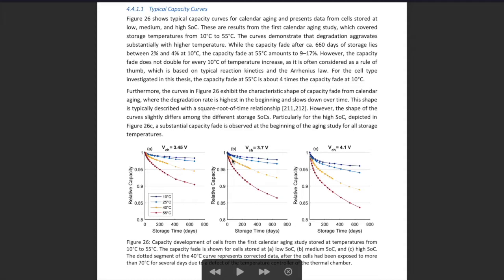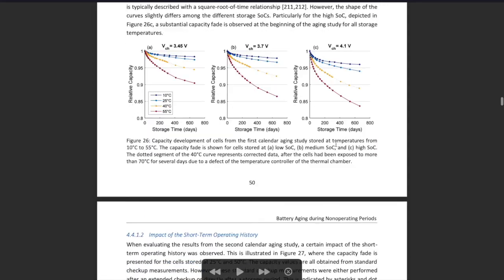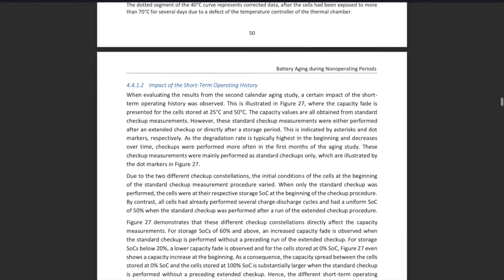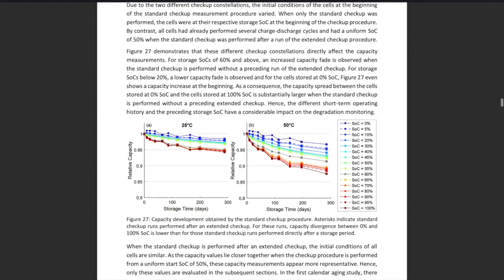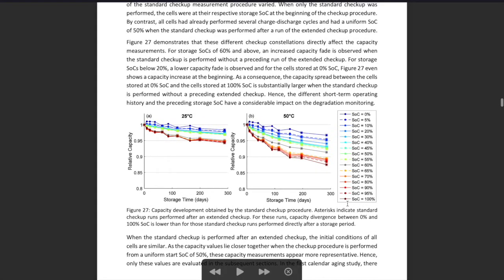You see the aging is not very strong, depending on temperature of course. But with a very high voltage corresponding to close to 100% charge, your aging is dramatic. The other curves confirm these findings. What we want to do is keep the state of charge low when we don't need the MacBook.